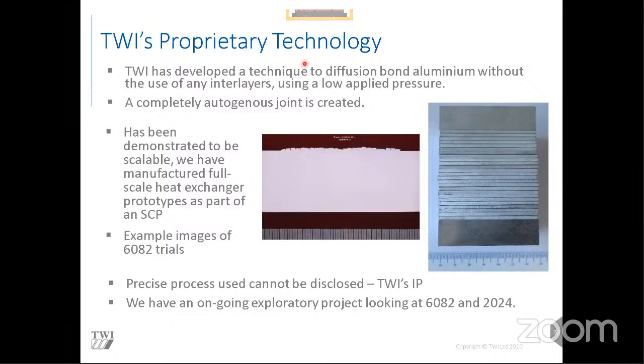Have you tried joining titanium and nickel alloys using diffusion bonding? I haven't specifically. Titanium alloys are very easy to diffusion bond, they're one of the nicest materials. The biggest issue with them is they're very susceptible to any oxygen contamination, so you have to be very careful. Nickel alloys are also diffusion bondable, but you've got to be very careful with what the grade is, because some of them have quite a few additives in there, and they've got very specific microstructures which you might disrupt. Generally, nickel alloys are diffusion bonded at high temperature. Titanium alloys depend on the grade - again this is very grade specific. They often have an alpha-beta transus temperature you don't want to go above, so you've got an issue where you can't take the titanium too high. So looking at those two materials together, you're probably looking at some sort of transient liquid phase type diffusion bonding process using some sort of interlayers.